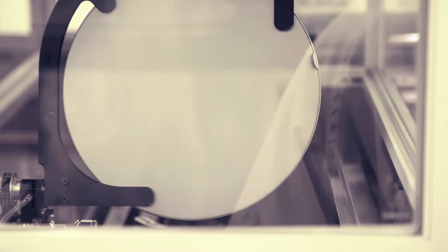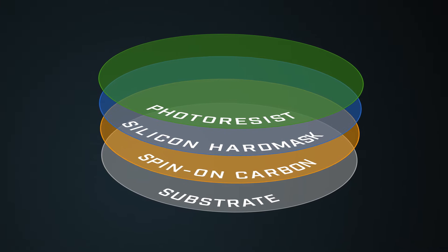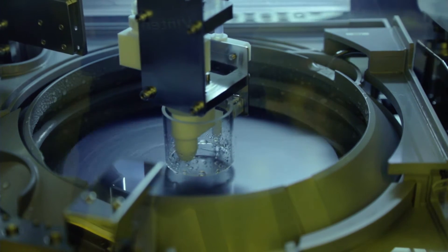What happens with the planarizing bottom layer is you really improve your depth of focus, and now you get a flat film to do your exposures on. On that you build a hard mask, and you can actually use a very thin photoresist, which improves your resolution quite dramatically. By moving to a multi-layer setup with a silicon-containing hard mask on top of a high-carbon-content SoC layer underneath, you could rely on etching just into the hard mask — that's all the resist would have to do. And that structure gave you enough resistance to withstand the etching process for transferring the pattern into the substrate.